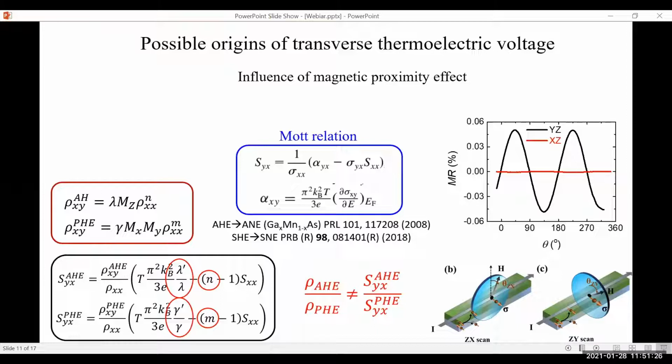If it produces any sort of AMR signal, that immediately implies there is a bit of conducting magnet, and that is due to the proximity effect at the interface. This data is for tungsten, and the red curve is the AMR, where we don't see any significant proximity effect. So we conclude that TMIG tungsten has negligible proximity effect.